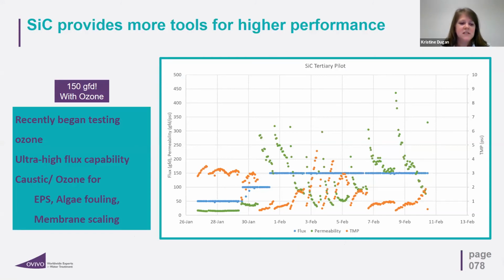The plant uses residual dewatering polymer, and that creates a lot of fouling for any kind of membrane. In spite of the polymer, at the pilot we have been able to achieve 100 GFD for 3 weeks. We also have done testing with ozone to see what kind of benefits that could bring, and with the ozone testing, have seen that we can achieve 150 GFD for a very long time. So the pilot has shown that we've got that ultra high flux capability, that we can achieve very low phosphorus levels, and that we can use caustic and ozone for plants that would have EPS, algae fouling, or membrane scaling.